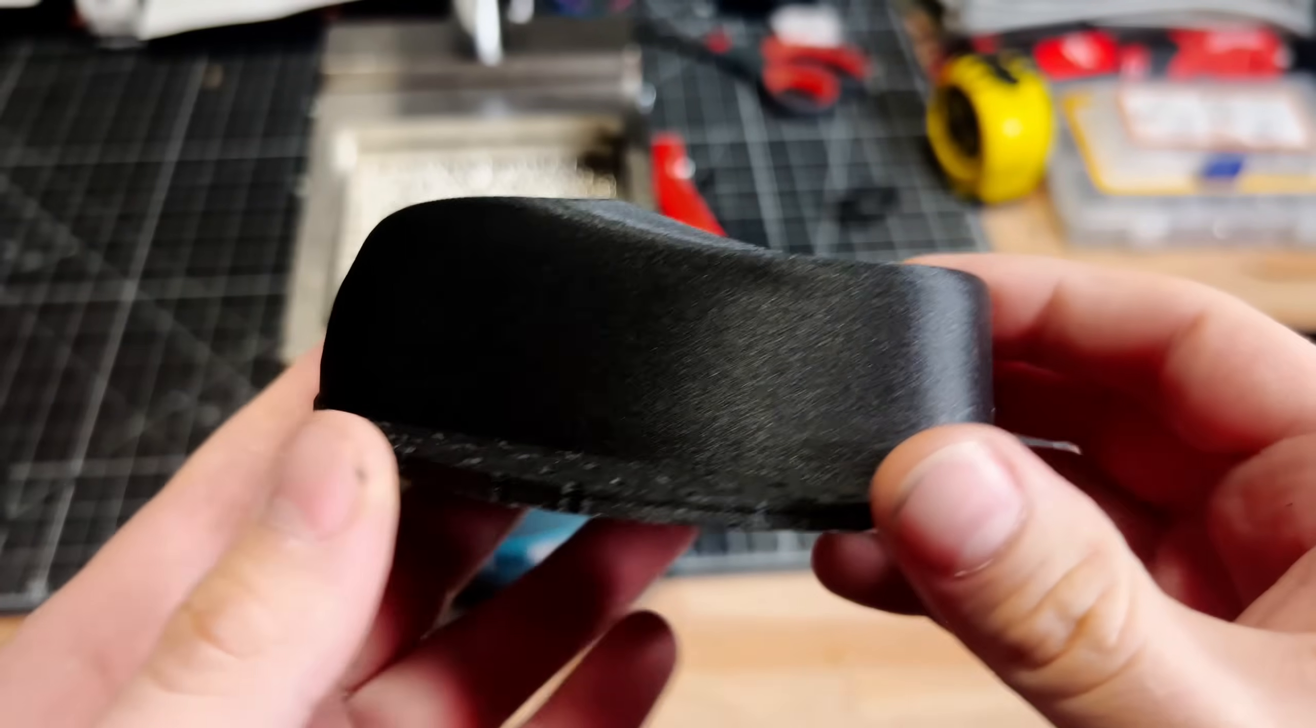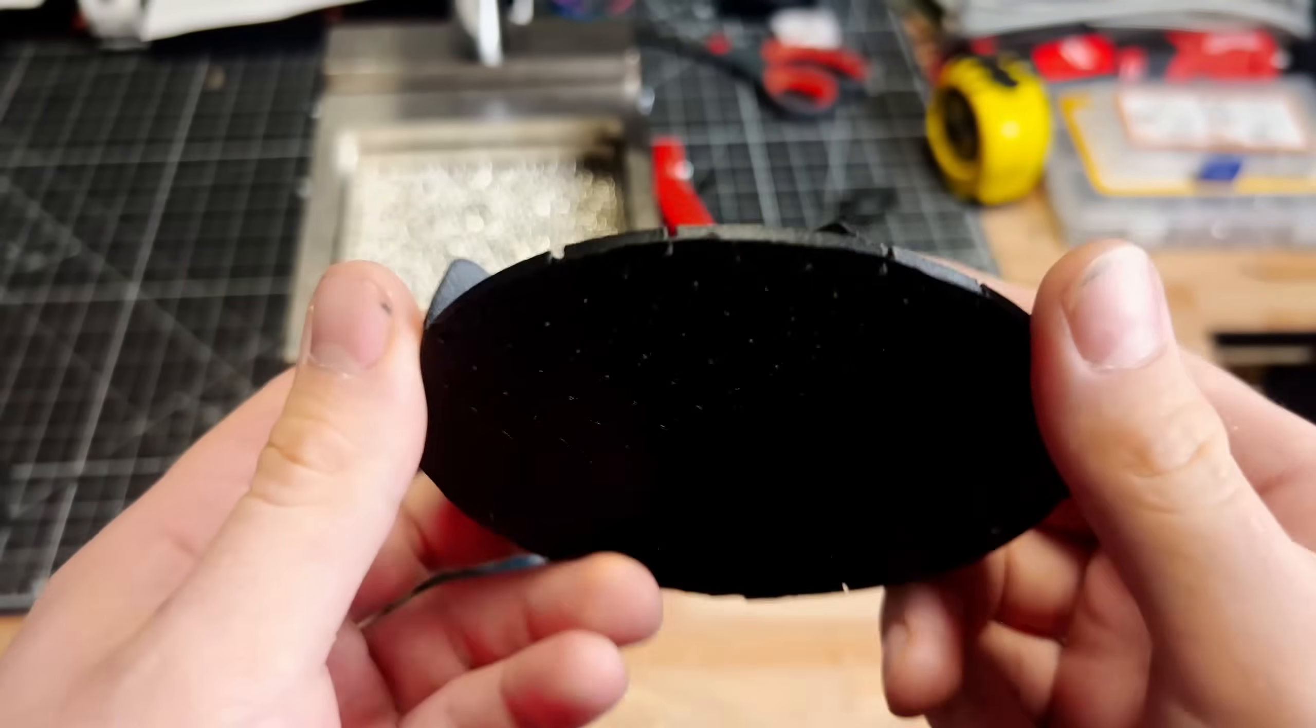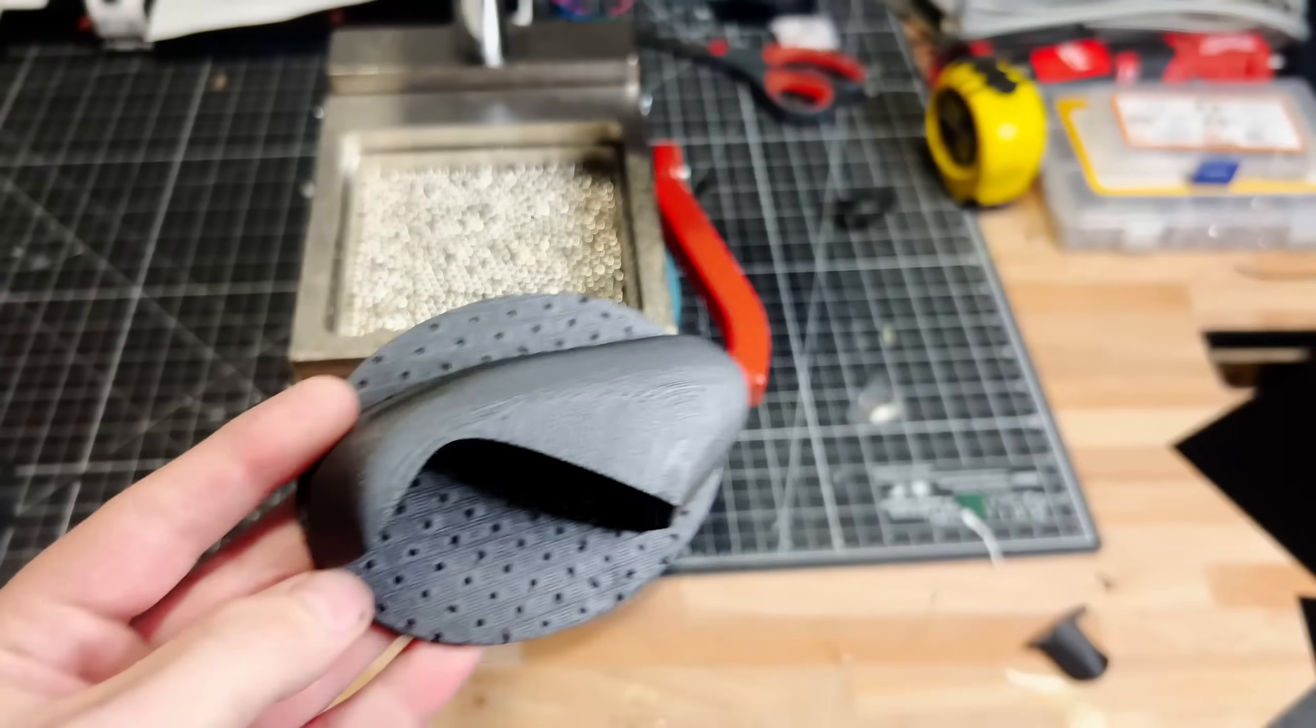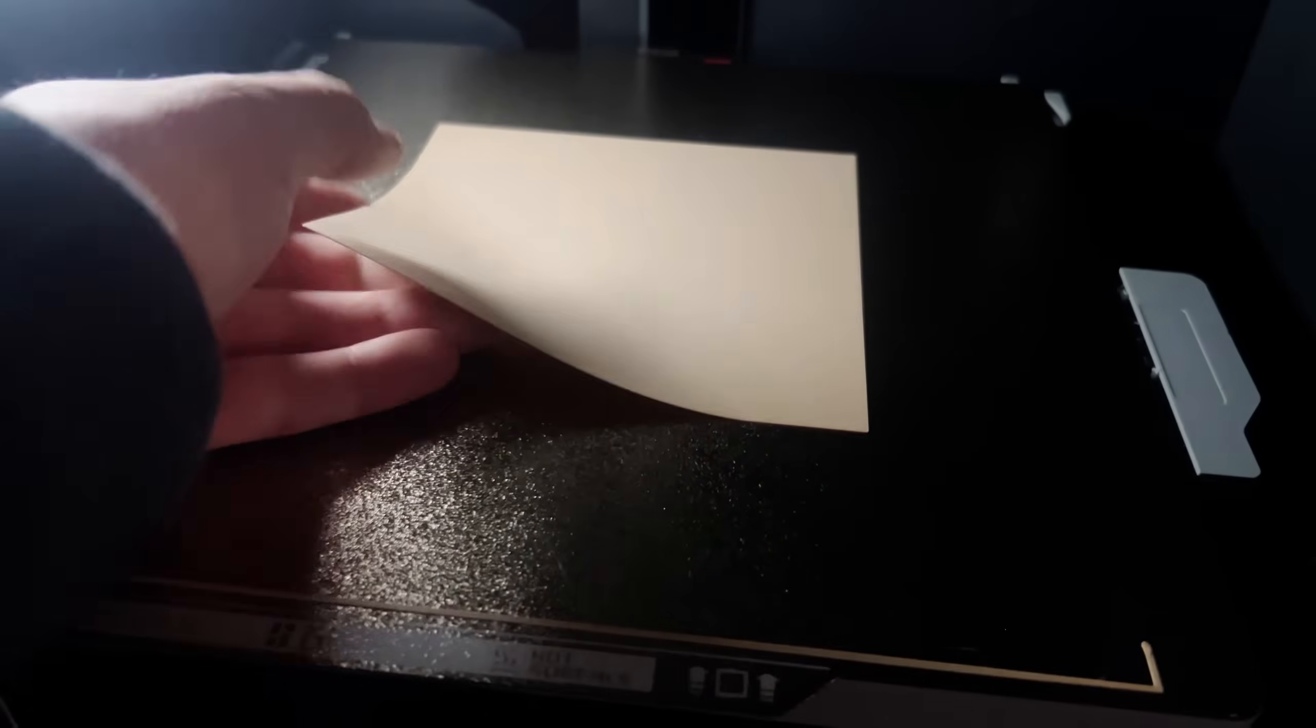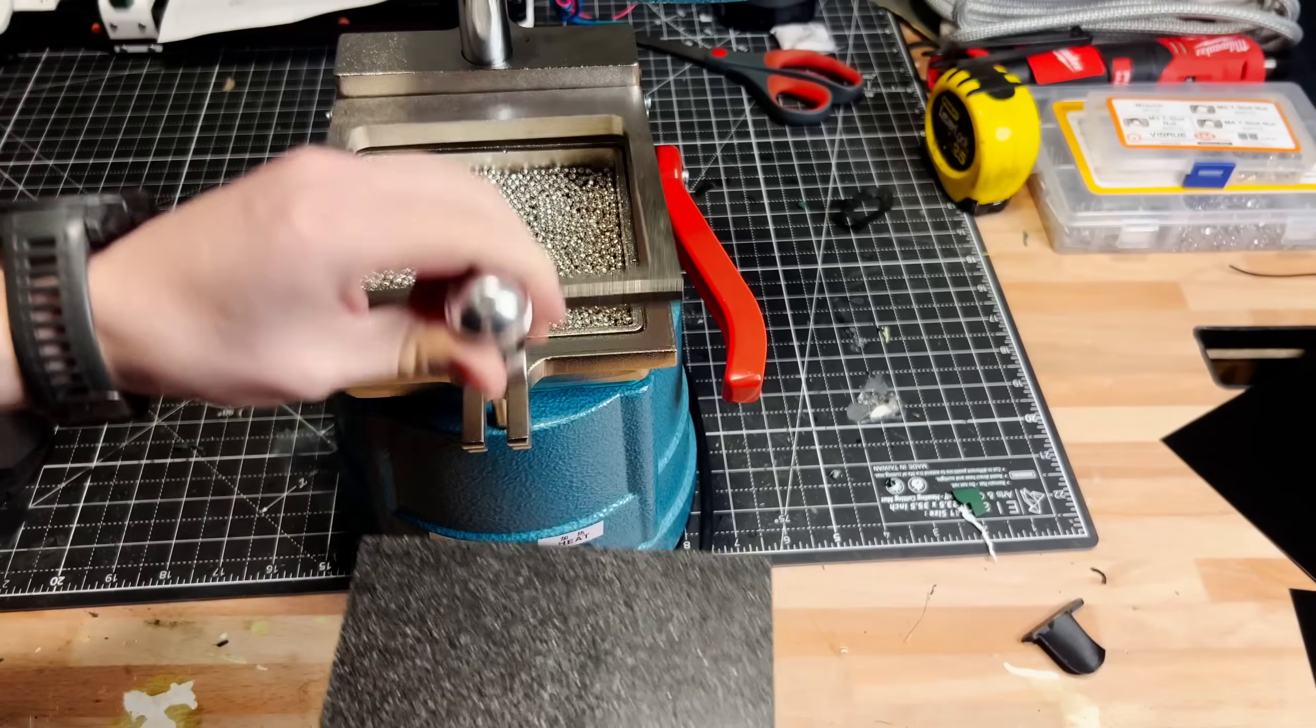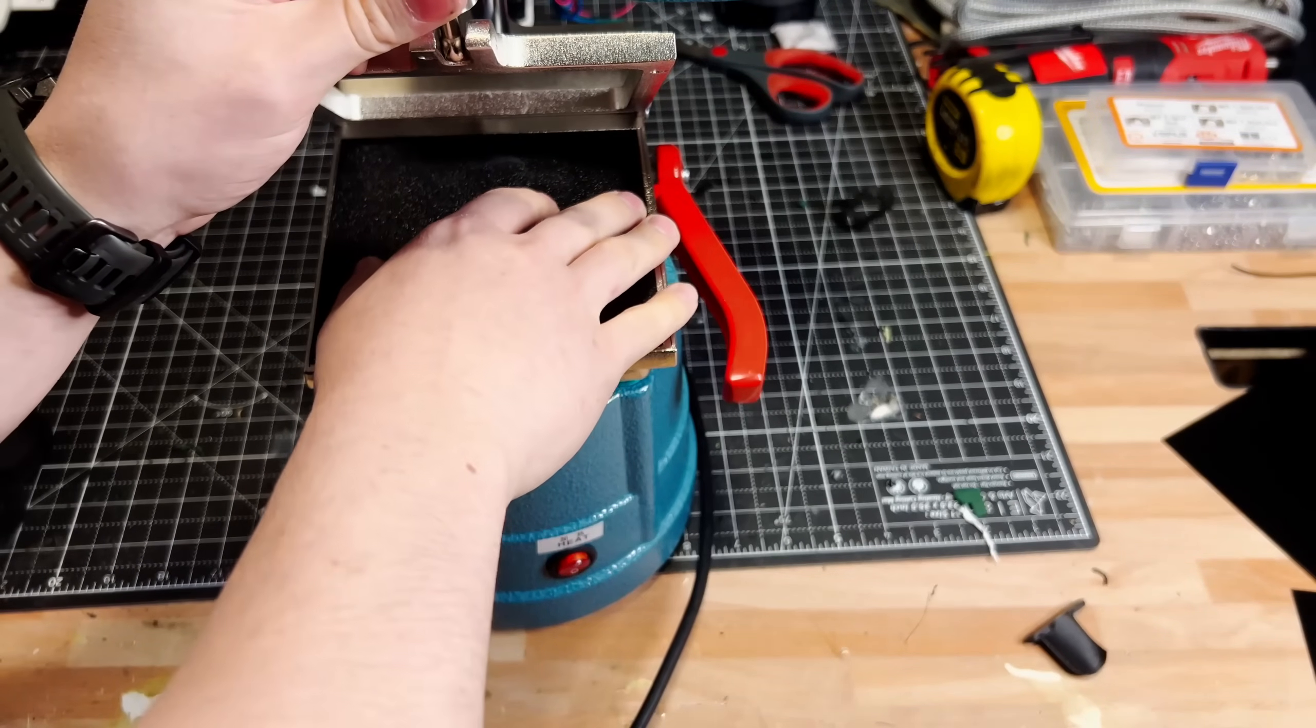Now that analysis is done, all that's left is to print the mold and thermoform sheet. The mold is carbon fiber PETG, and the thermoform sheet is PETG printed at 0.64 millimeters thick on my printer at 130 by 130 millimeters. The sheet is then installed into the clamp system of the vacuum former and raised up for the mold to be placed underneath.